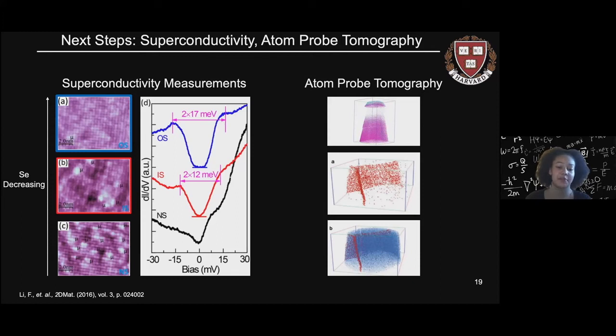atom probe tomography. As you can see in these images here, atom probe tomography allows you to replicate a three-dimensional image of your material and see exactly where each atom of different elements is located. So by using this technique, we would be able to see exactly where the selenium atoms are when they're diffused into the strontium titanate bulk. And this would provide us with more clarity about the structure and characterization of the interface of our material.